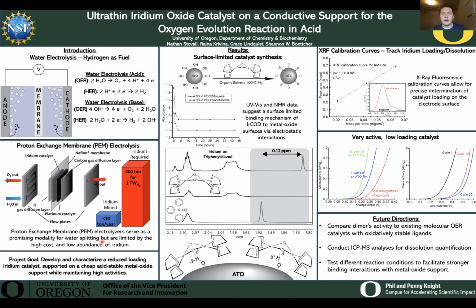This led to our development of a novel synthetic method in which we can soak antimony doped tin oxide, or ATO, nanoparticles in an organic solvent with this iridium dimer we call iridium cod. When you apply mild heat in a nitrogen atmosphere, you can adhere iridium to the surface of this ATO. We wanted to look into the mechanisms by which these were binding to each other. So first we did a UV-Vis experiment in which, as the reaction ran, we tracked the absorbance of our iridium cod dimer over time.